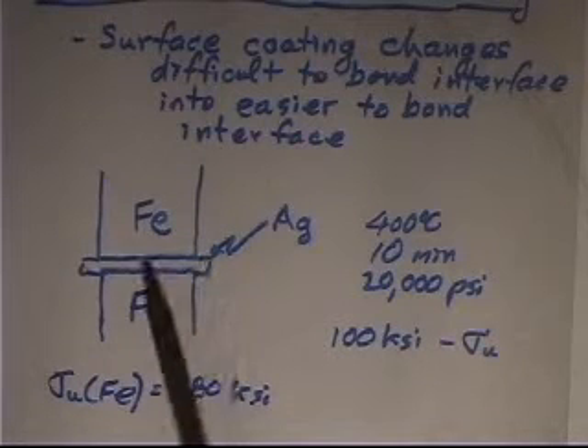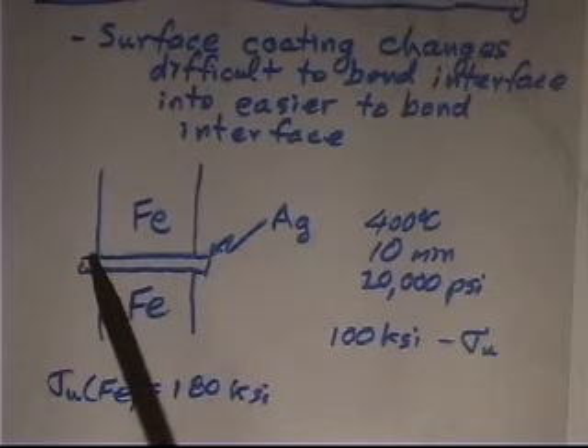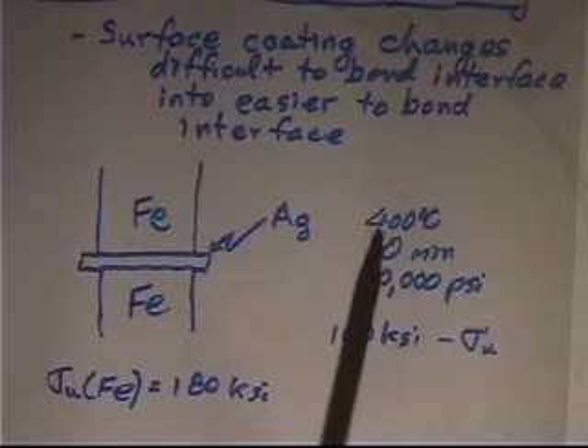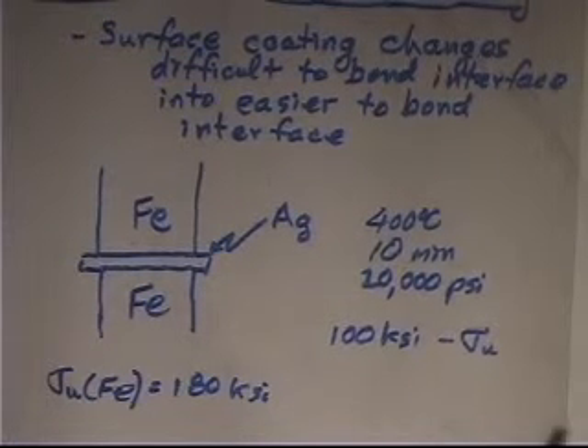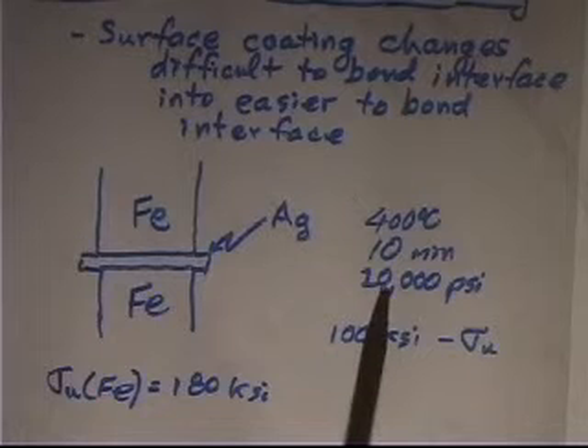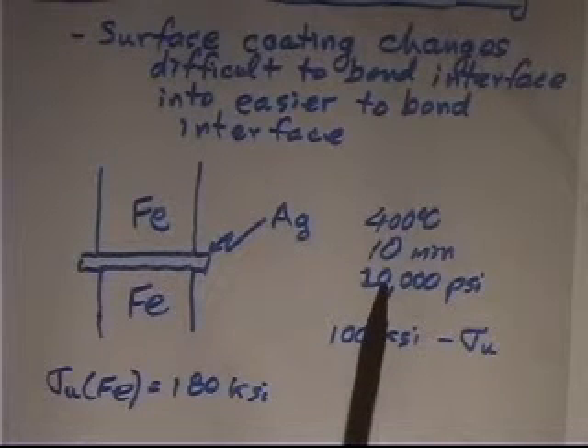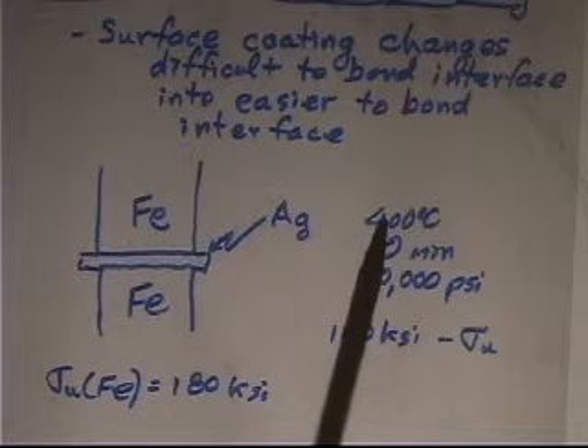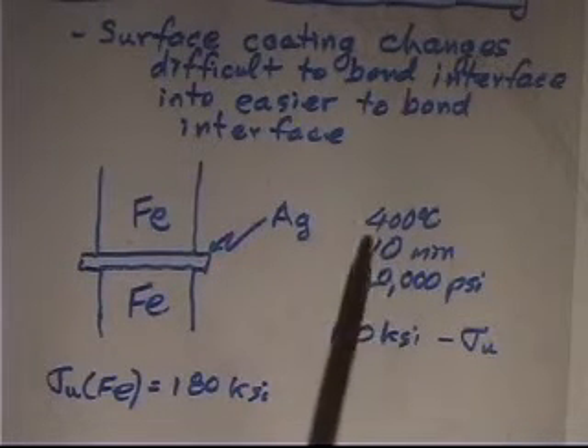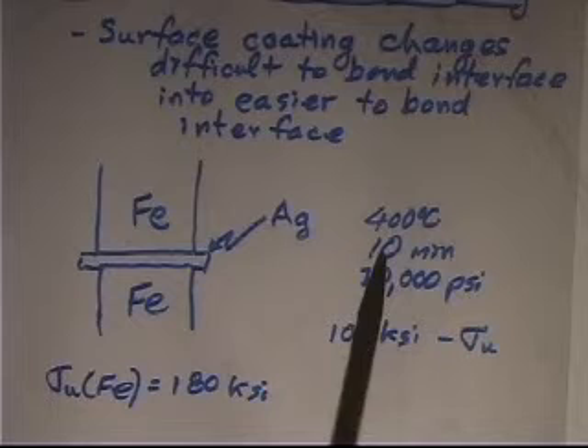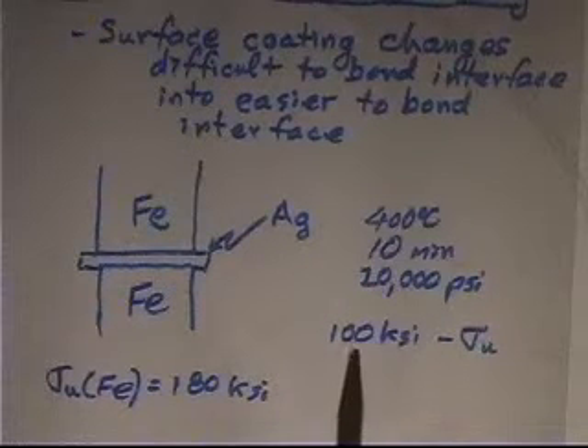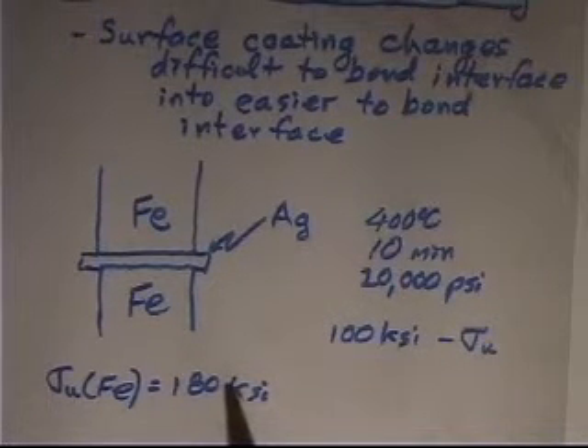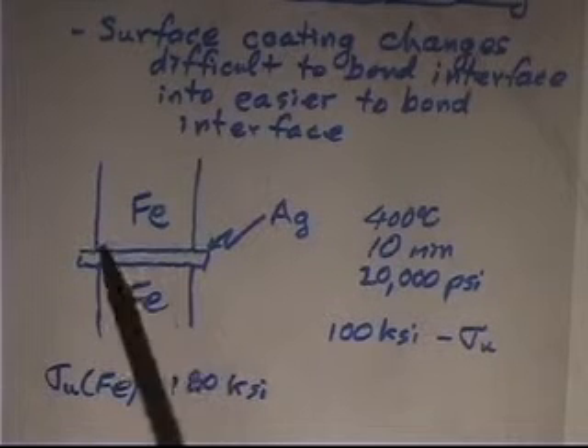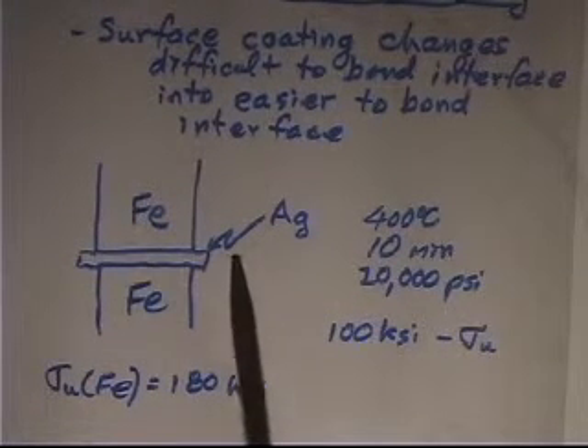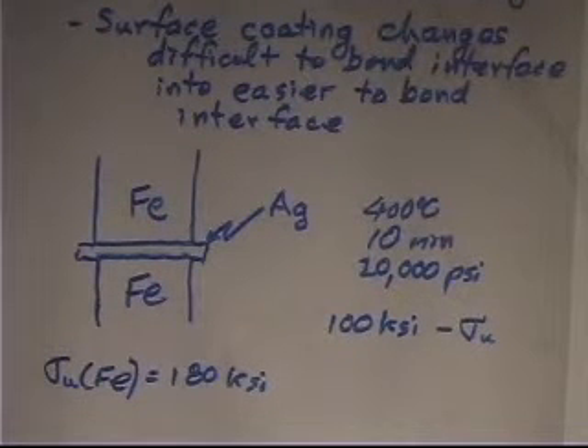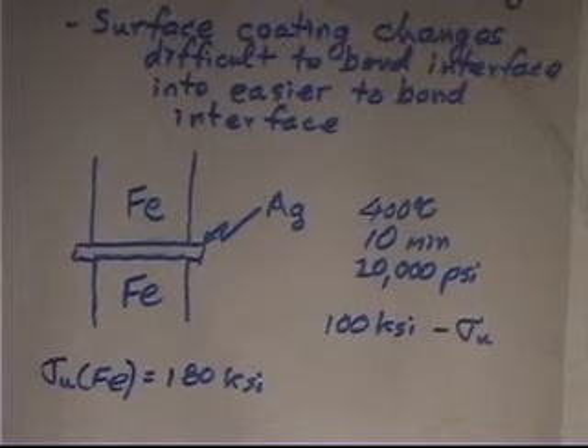And they were able to achieve a bond by putting an inner layer of silver at the interface, a diffusion bond, at 400 degrees centigrade in 10 minutes and 20,000 psi bonding pressure. Now, 20,000 psi bonding pressure is a pretty high pressure. They don't melt silver at 400 degrees centigrade. It melts at around 961 or 962 or something like that centigrade. But 10 minutes is a pretty quick bonding time. And when they put this all together, they got 100 KSI bond strength. And really what they're doing is they had already plated the iron with the silver in a chemical process and then put this whole thing together and bonded silver to silver. Because silver to silver is an easy thing to bond.